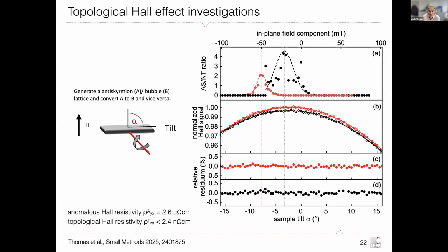So what we do now is we subtract this trivial geometric contribution to the signal, and we end up with what we call the relative residual, which is the difference between the expected change of the Hall effect due to the tilt. And as you can see, this is within our experimental resolution, I would say, pretty much a straight line. And so is the black one, which is the other tilting direction.